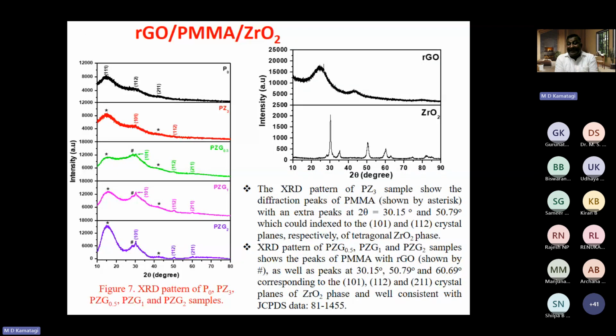Now, then we have characterized this film. The idea was to see whether the doping of reduced graphene oxide enhances the mechanical properties as well as the photoluminescence properties. ZrO2 is crystalline in nature, whereas graphene oxide as well as polymers are amorphous in nature. So this is pure PMMA. This is 3% of ZrO2. We can see the peaks of ZrO2 corresponding to peaks of PMMA. They are well merged. That means the incorporation of ZrO2 has happened.